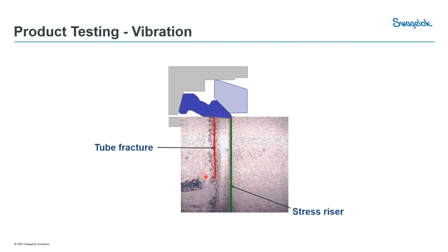Now, why is this and what does that mean? Really what we've created with this back ferrule of the Swagelok tube fitting is a long region, we call it the collet region, where that ferrule is gripping onto the tube. So it's really gripping it, especially in that vibration. That force that would normally be pointed on the stress riser is spread across the tubing. Now this allows it to last much longer, especially in vibration service. And that's why you have the resulting tube fracture further throughout this collet region.